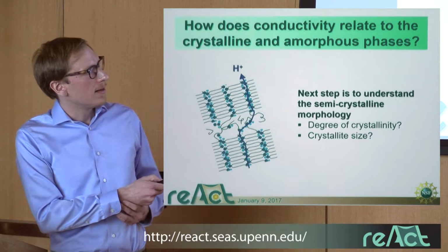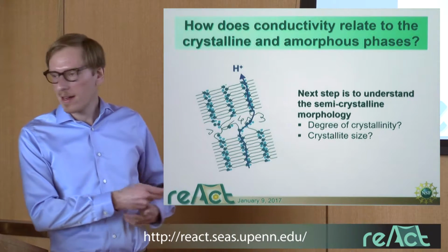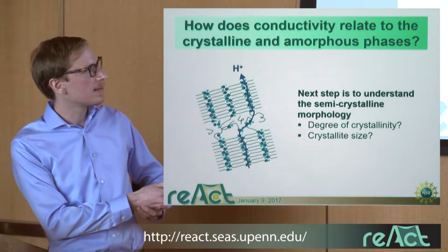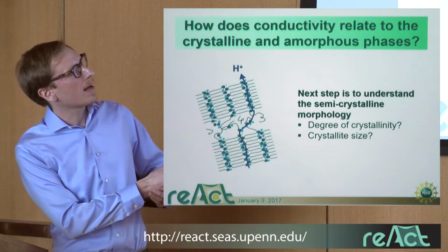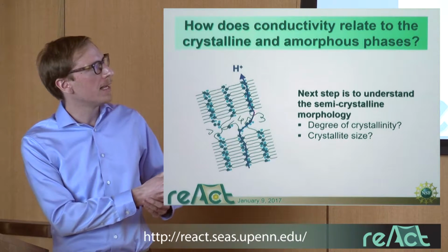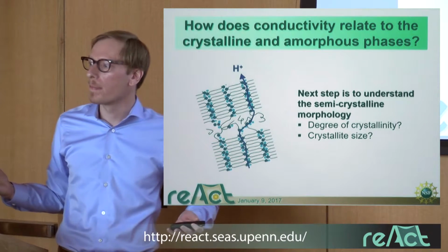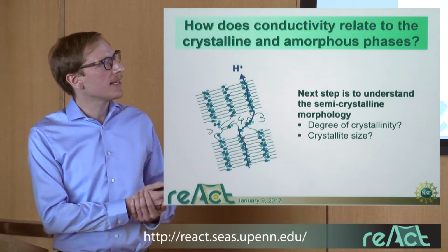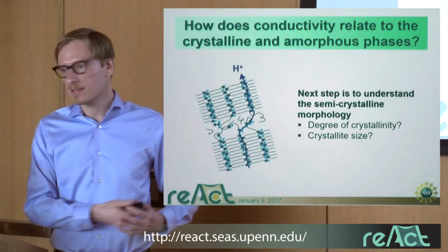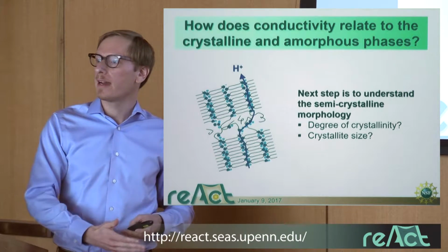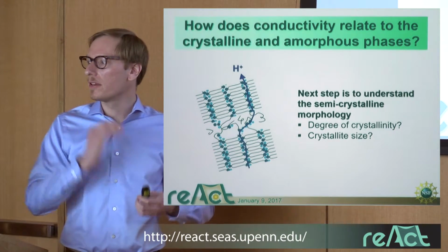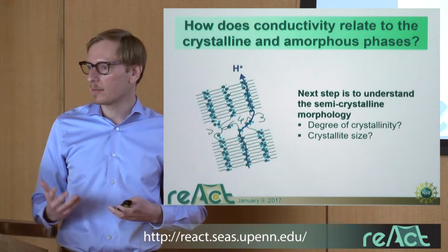So for example, our protons in our conductivity measurements are protons moving through a layer and then kind of making their way through an amorphous domain to get to the next layer. So we need to understand how the degree of crystallinity is going to affect the conductivity. For example, we can reduce the degree of crystallinity by quenching the system from the melt.